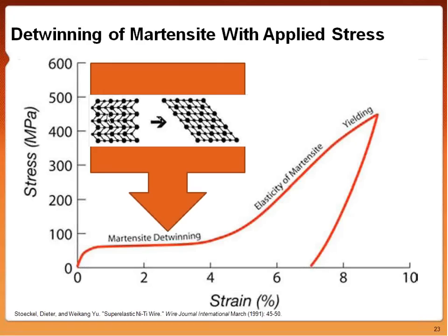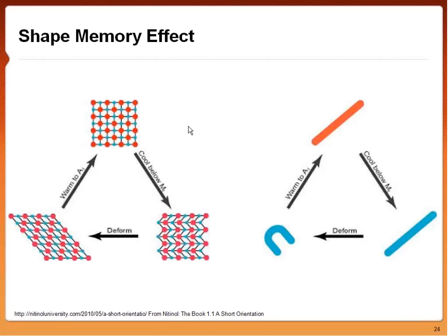So you can see in this projection of this crystal structure over here, we go from the twin martensite form, and as you can see, we apply slight shearing in this direction to move to this structure. So if we combine our understanding of nitinol thermodynamics, moving from one crystal structure to the other, we get what's called the shape memory effect.